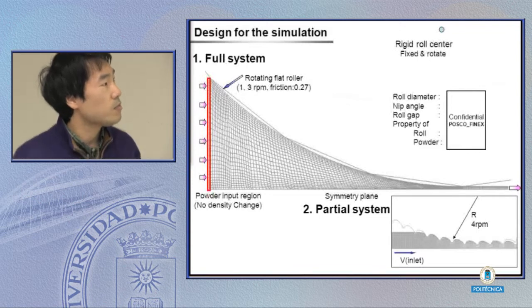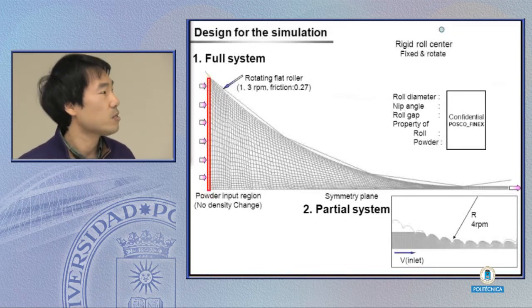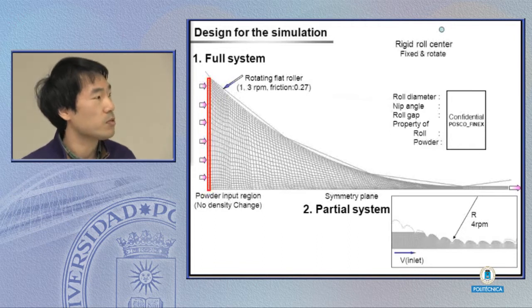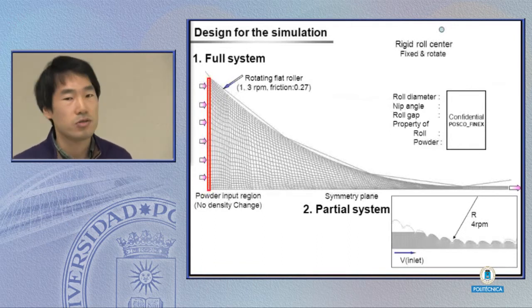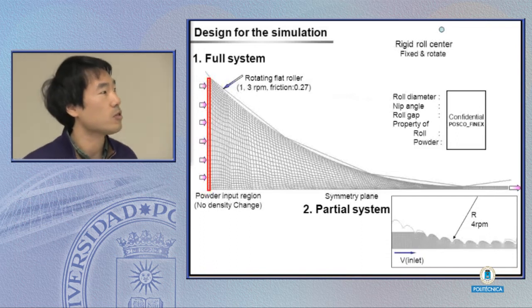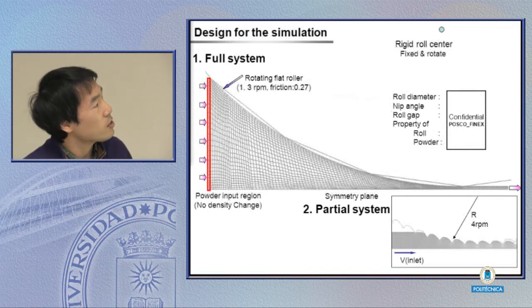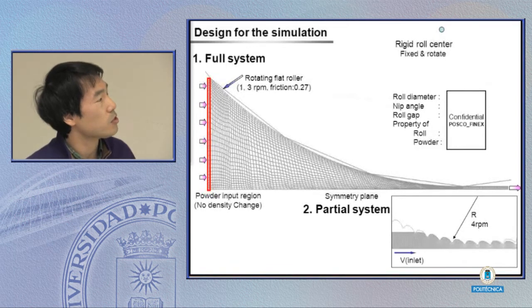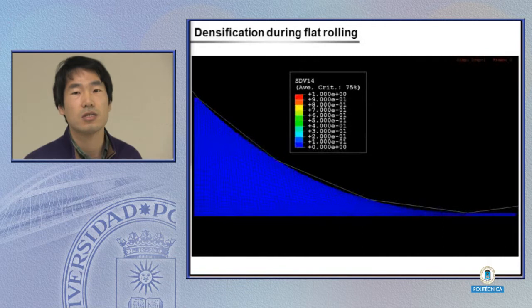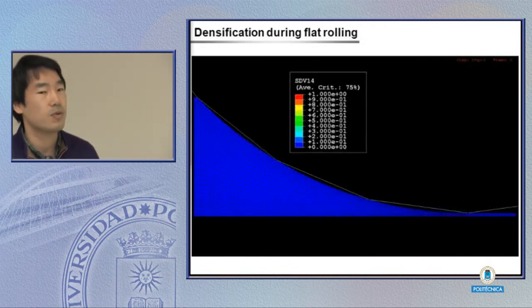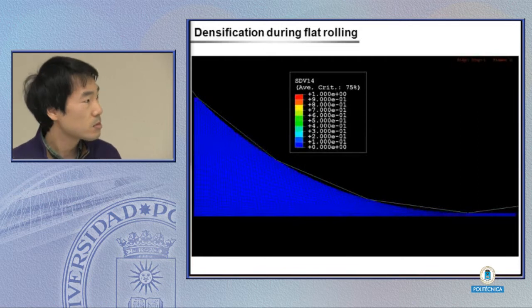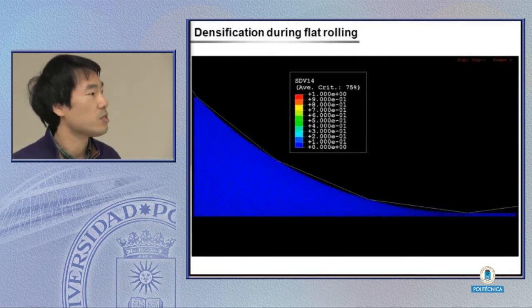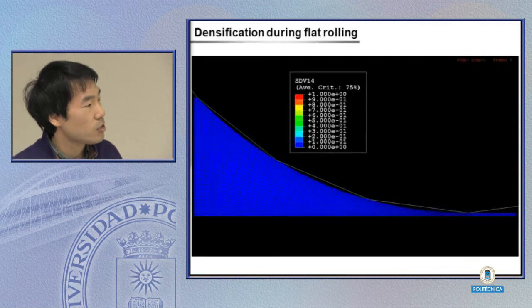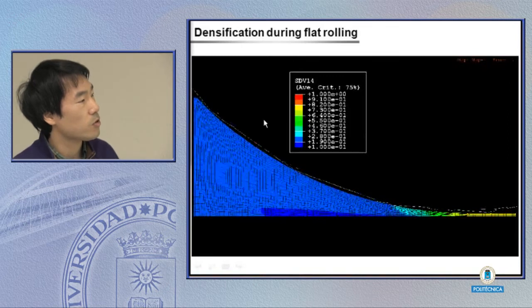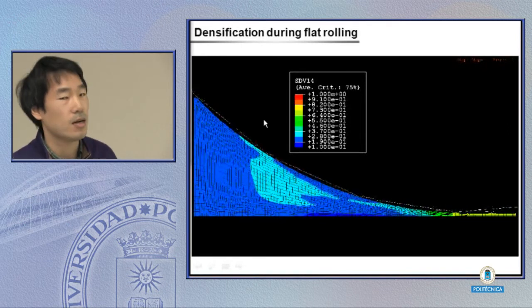Here is the mesh design for simulating the powder compaction. Although I can't tell you the exact quantities due to confidentiality, I can show you that the inlet powder length is much higher than the outlet length, which is a very severe deformation simulation. But with ALE, we can do the simulation. And to see the roll surface pattern effect, I simulate only focusing on the surface roll gap part.